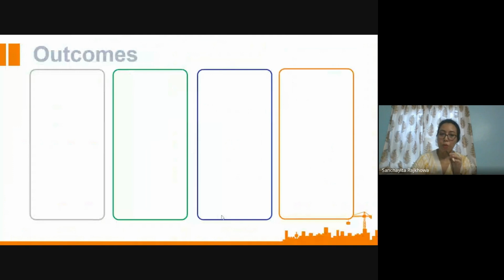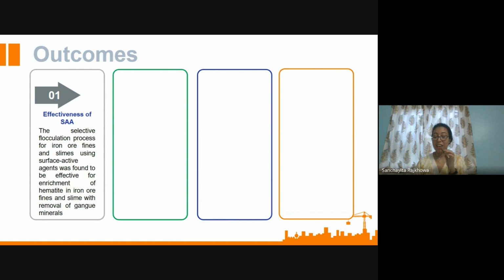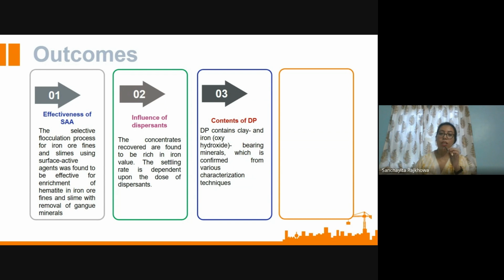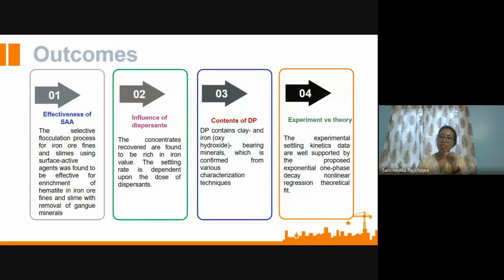So what are the outcomes from this study? Although I have tried hard to sum up in 15 slides, it gives us the effectiveness of the surfactant agent, which surfactant agent will be more effective in extracting iron from those waste materials, what is the influence of the dispersant, and how the settling rate is dependent on the dose of dispersant from that first order kinetic study. And then we could know the content of the dispersed phase from those various analyses. Then lastly, of course, experiment versus theory, and this experiment is well supported by the theory.